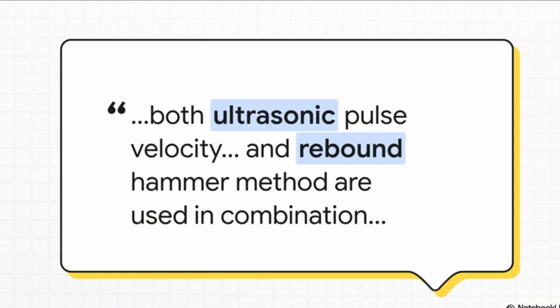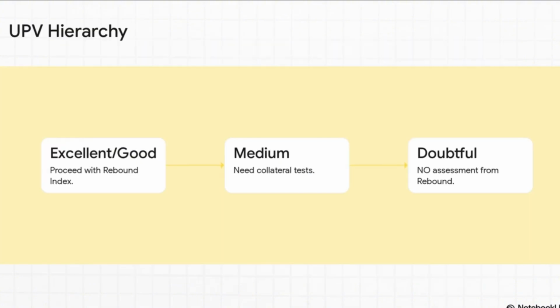Because of this surface-level limitation, the standard is incredibly explicit. It states that it's preferable to use the rebound hammer in combination with ultrasonic pulse velocity, or UPV. Now, UPV is a dynamic test that sends high-frequency sound waves deep through the entire mass of the concrete. It measures exactly how fast those waves travel. Solid, dense concrete transmits sound very quickly, but cracked or honeycombed concrete slows the sound down. So UPV acts as this deep scanning diagnostician, making it the perfect and honestly necessary partner to the surface-level rebound hammer. Let's see how this builds into a strict conditional framework for engineers out in the field.